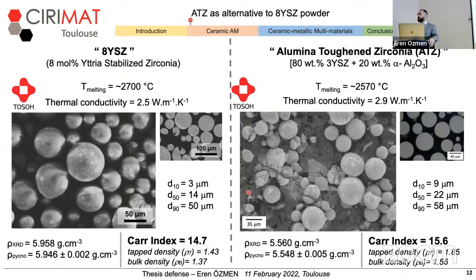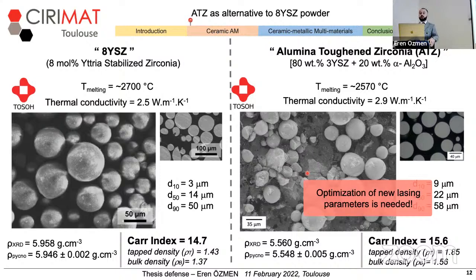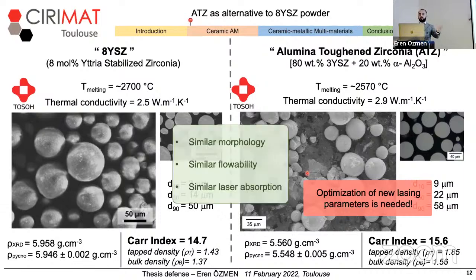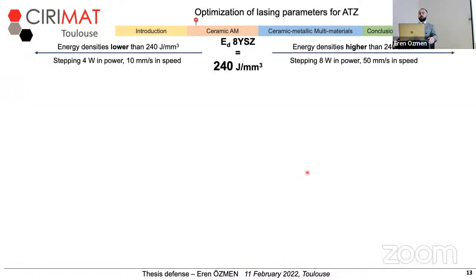a very similar morphology powder was supplied. As we can see here, they are both spherical, almost fully dense, and have similar flowability. And alumina toughened zirconia was a good candidate for this process. However, due to its different chemical composition, a new lasing optimization was needed. As their morphology, flowability, and laser absorbency are very similar, I took the energy density needed for 8YSZ fabrication as a reference point.